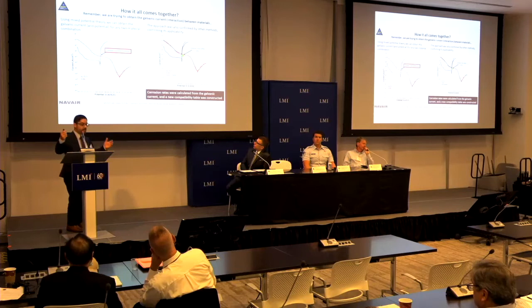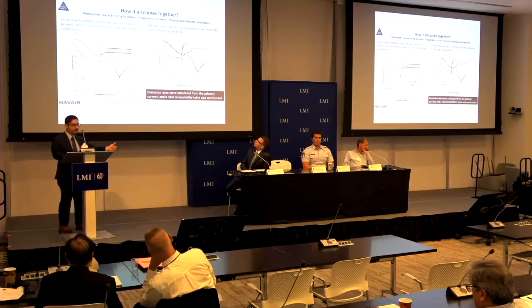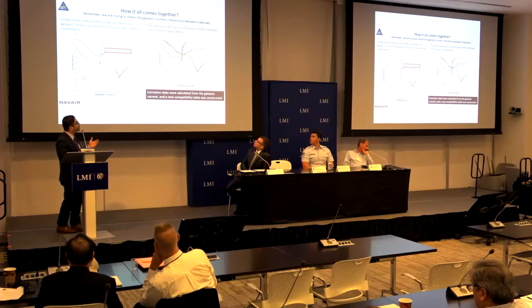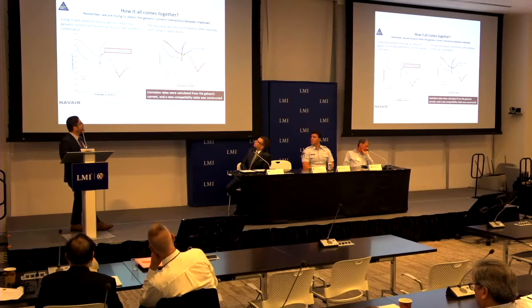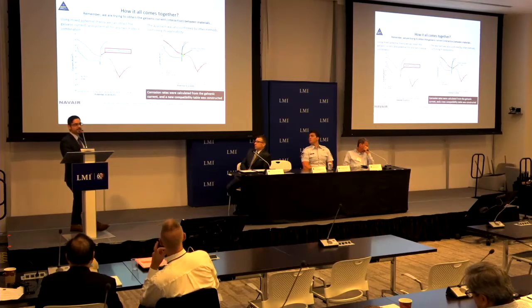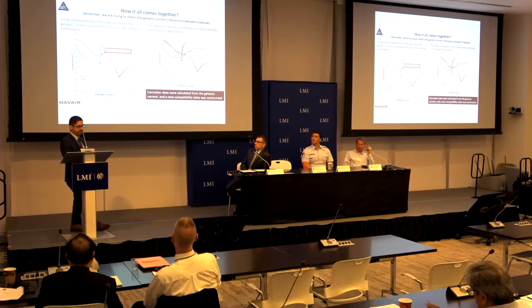So basically, this is how it all comes together when you collect all that data. You collect this data on individual metals, right? And you put them together, right? Where they meet, that's where you obtain your galvanic potential and your galvanic current. We also used other methods to verify that this approach was an appropriate approach. So from here, you obtain the galvanic current, which you can then change into a corrosion rate. A corrosion rate tells you how much of that material is corroding away as a function of time, right? So that's how much you can expect, let's say, aluminum to corrode away when you pair it with a stainless steel. And by the way, now that I mentioned stainless steels, it's a misconception that stainless steels don't corrode. They do corrode, and they corrode a lot, and they suffer from a lot of corrosion damage as well.